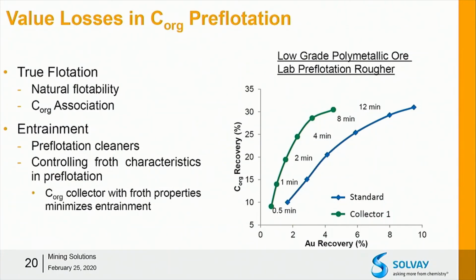And what's quite interesting about this is that it is a carbon collector. People think that carbon collectors make surfaces more hydrophobic to increase carbon recovery or increase kinetics. But if you look at the kinetic data there, there's no change in the actual flotation kinetics. It's purely a froth phase phenomenon. So actually understanding what the chemicals are doing can really have a substantial benefit to improving the actual metallurgy and optimization of the process.